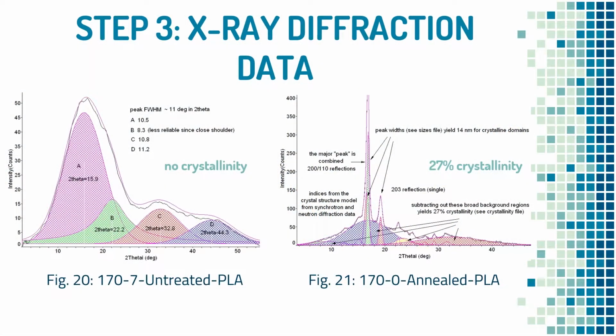So we can integrate these scattering graphs, and from that we can produce graphs of intensity versus 2 theta. Now on the left we have the graph for untreated PLA, and as you can see, it's relatively amorphous because there are no crystalline peaks. The peak you see here is an amorphous peak. So this tells us that untreated PLA has relatively no crystallinity. On the other hand, we have annealed PLA, and as you can see, this is a very sharp and defined crystalline peak. Now, in order to calculate percent crystallinity, we can take the area under this crystalline peak and divide it by the total area under the graph, and from that we can obtain the 27% crystallinity of annealed PLA.